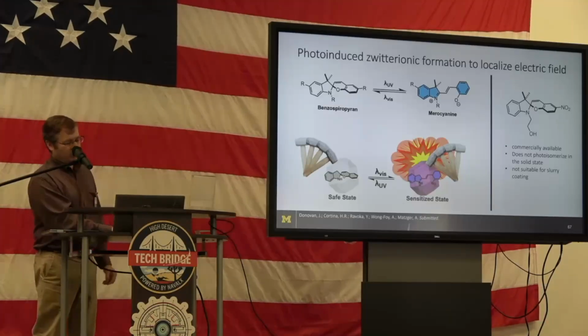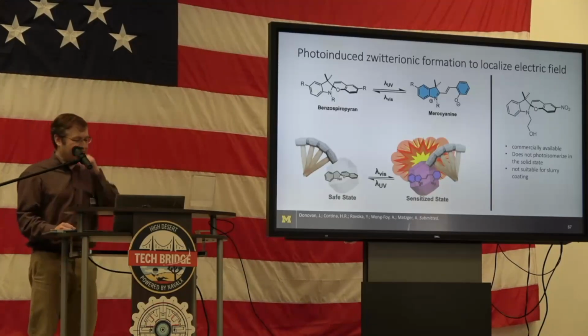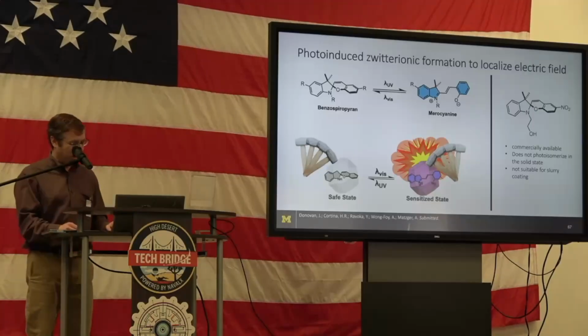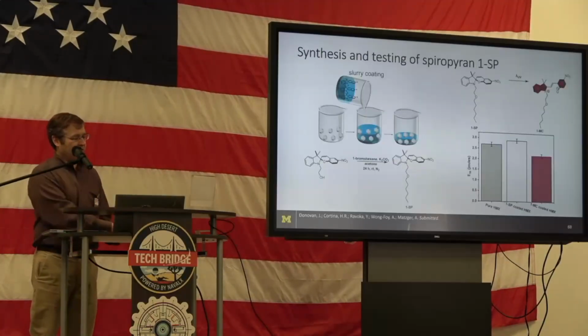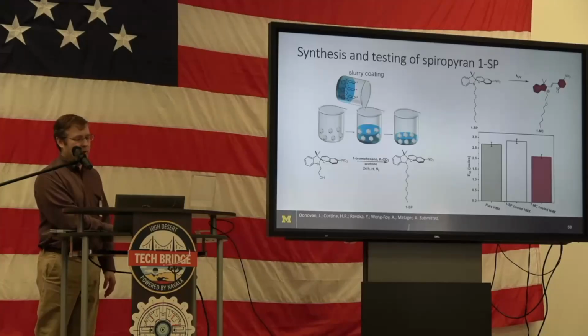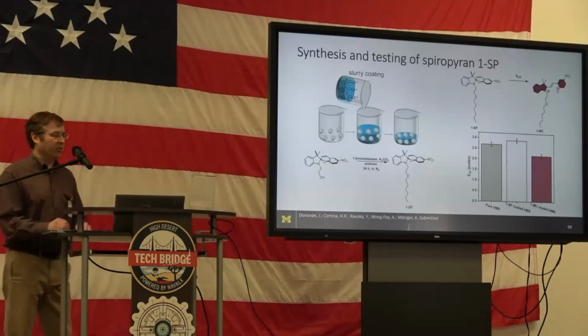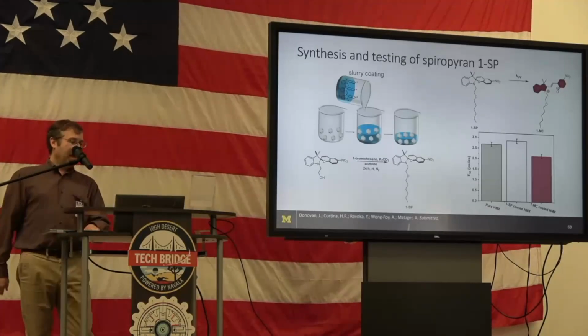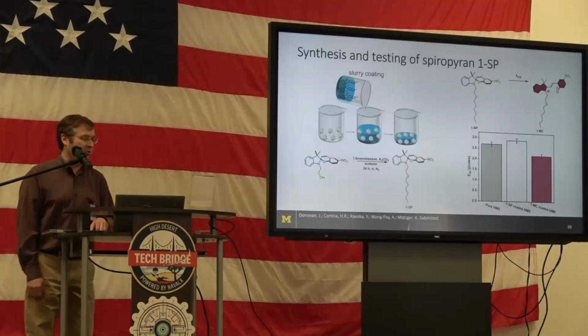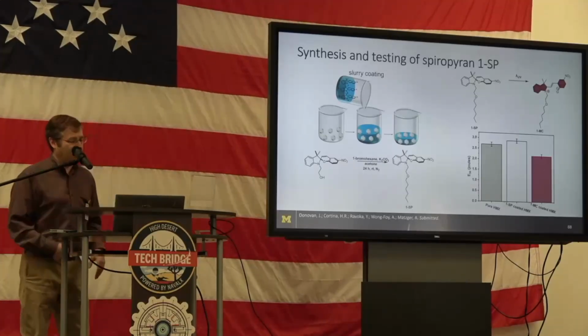This is commercially available, but it doesn't isomerize in the solid state. We couldn't really coat it on energetics well. So we just made a simple derivative. We added some grease to make it more soluble and impede the crystallization. And then we coated that with slurry coating onto HMX.